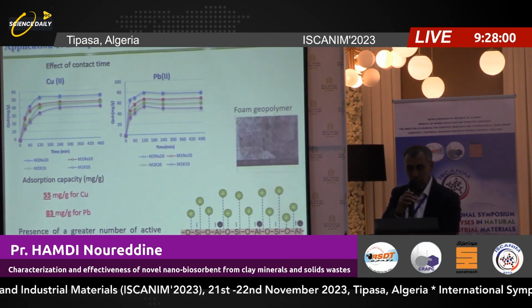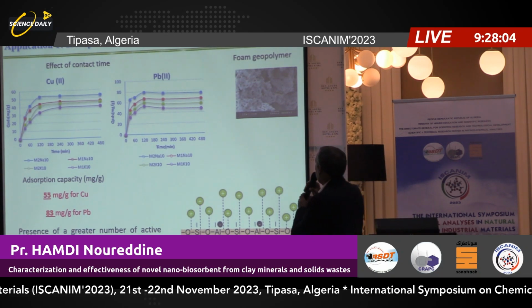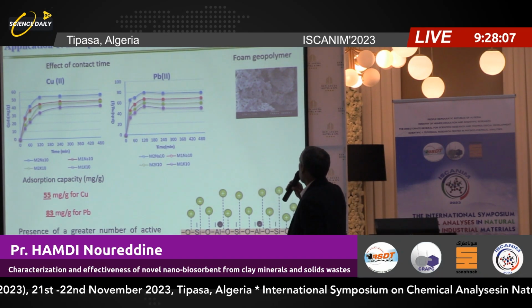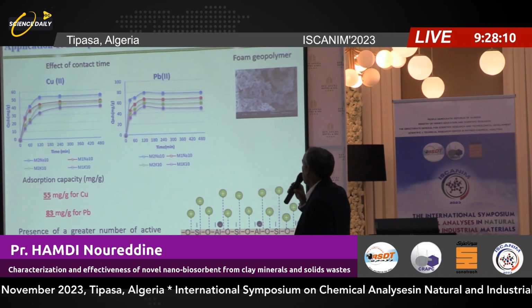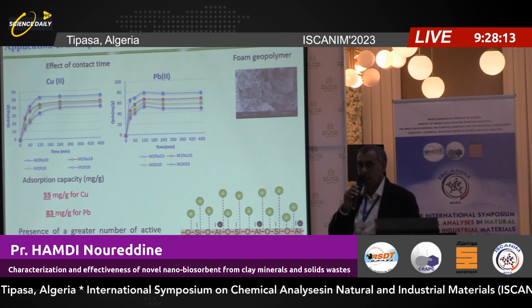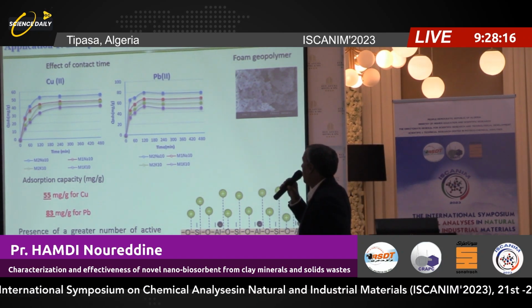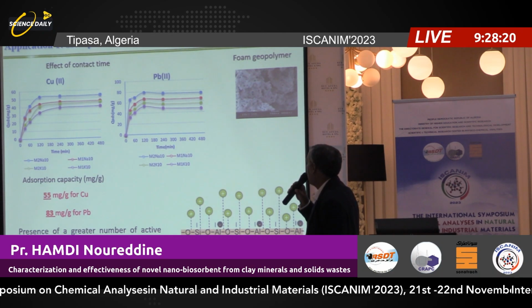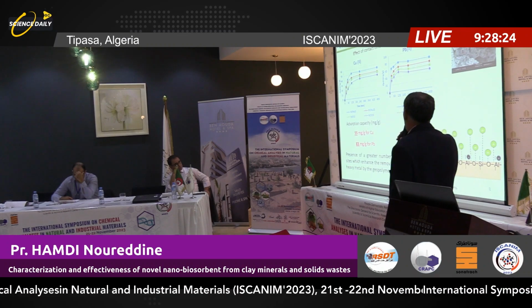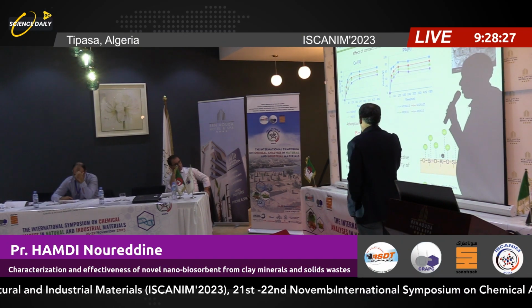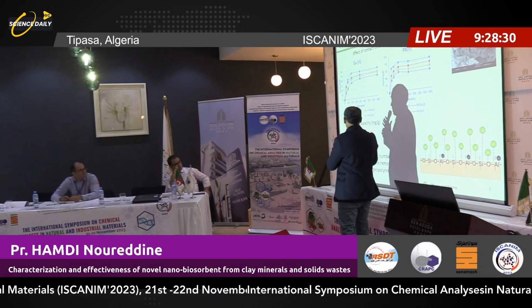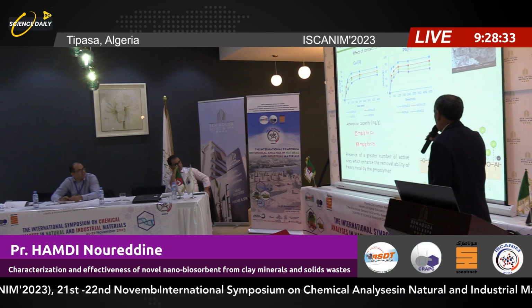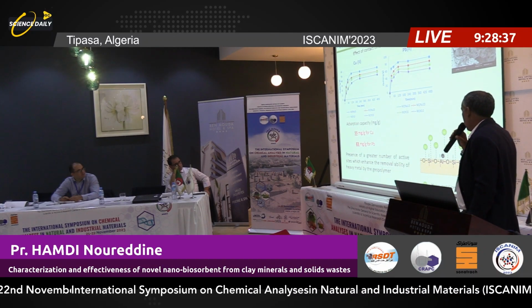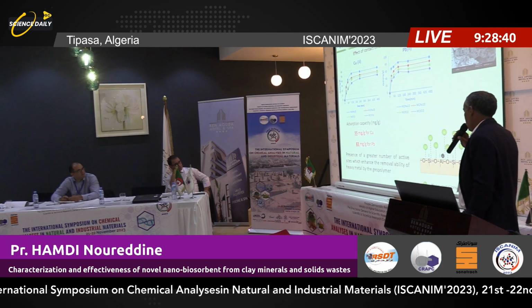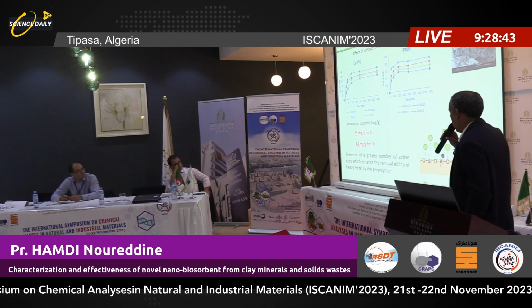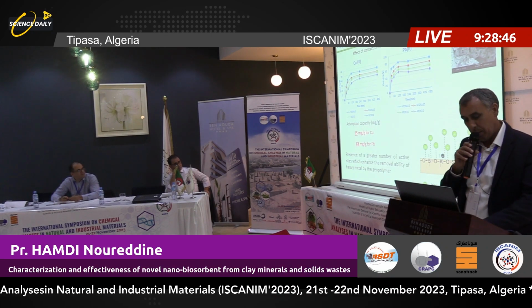The characterization by scanning electron microscope gives an idea about the microporosity and macroporosity of the geopolymer. After that, the first application of this geopolymer is in water treatment of the heavy metals copper and lead by adsorption. The kinetics is very fast, and the adsorption capacity is very high compared to other adsorbents, about 55 milligrams per gram for copper and 83 milligrams per gram for lead. The mechanism is in general that the active sites on the surface of the geopolymer adsorb these heavy metals.